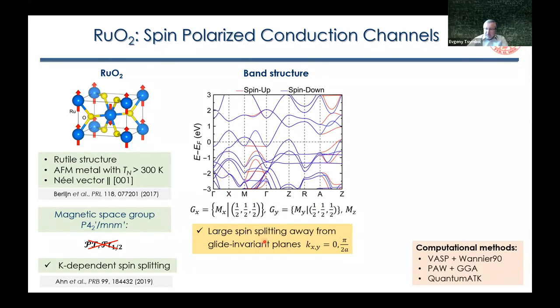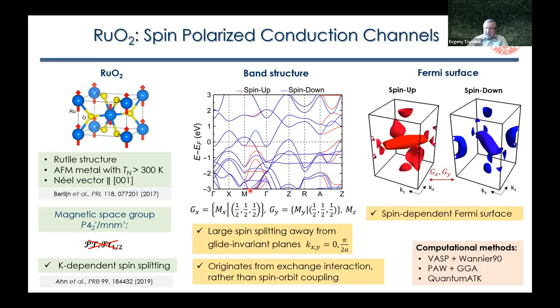But if you go away from these planes, for example, if we go along these two high symmetry lines, you see quite substantial spin splitting. What is important is that this spin splitting originates from exchange interaction. It's not due to spin orbit coupling, and therefore this spin splitting is quite substantial. As a result, we have spin-dependent Fermi surfaces, which are calculated and shown here.